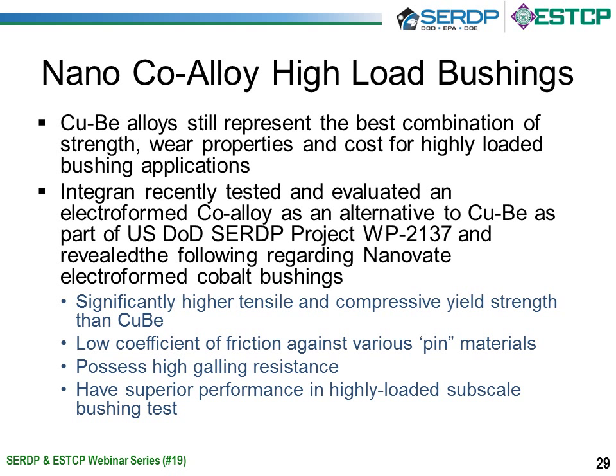And what we ended up with is we found that our electroformed cobalt alloy performed very well as an alternative and had a number of the interesting properties that copper beryllium has. So, it had significantly higher tensile and compressive strength than copper beryllium. It had a low coefficient of friction against various pin materials. It had excellent galling resistance. And it had superior performance in a highly loaded subscale bushing test that we performed.